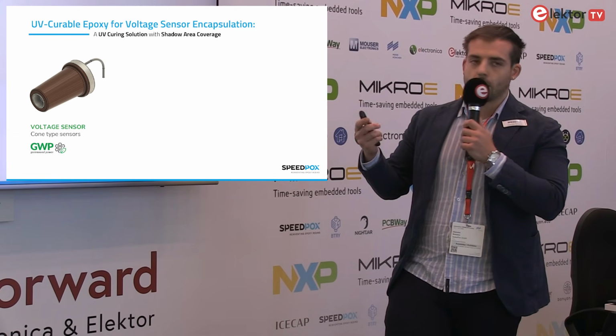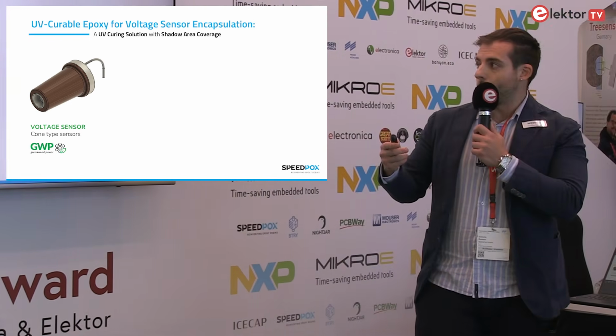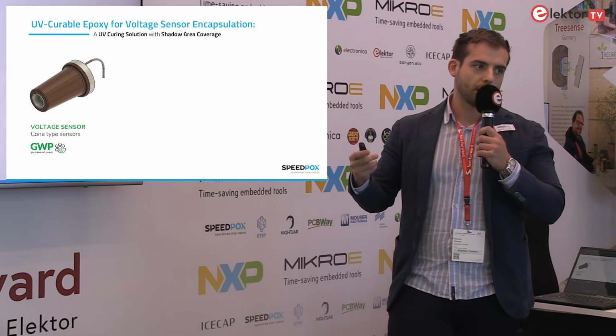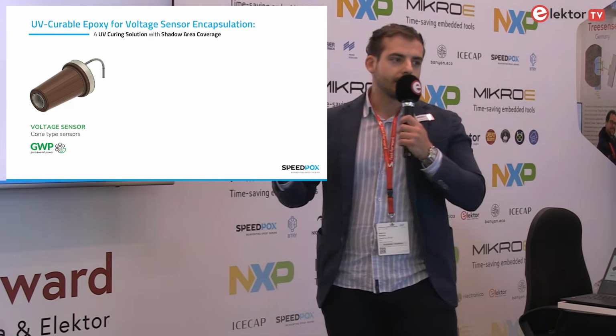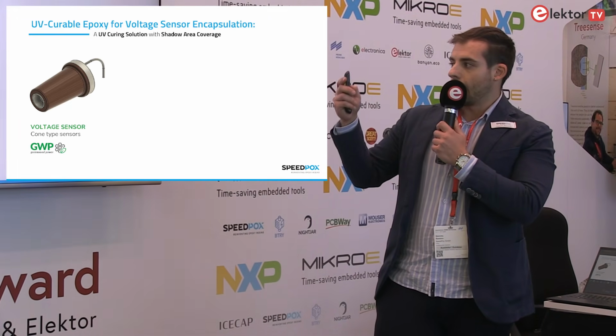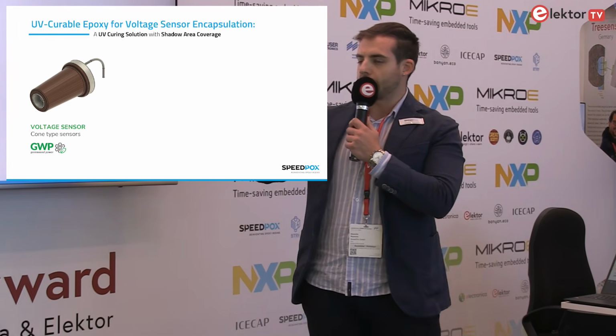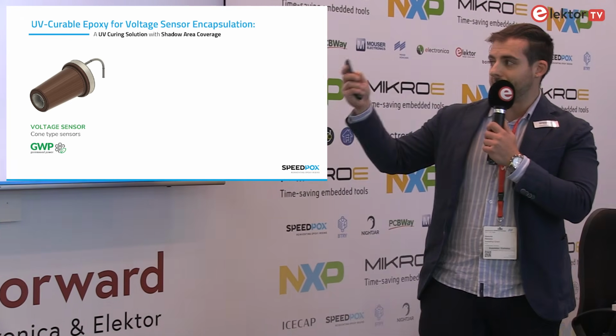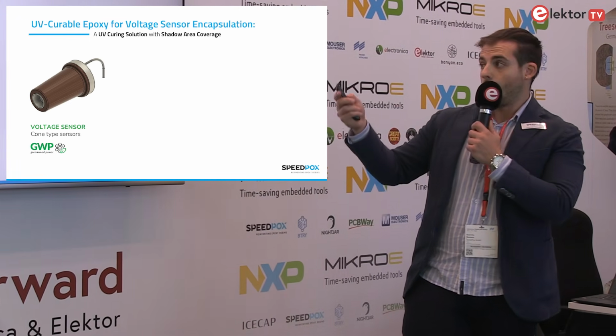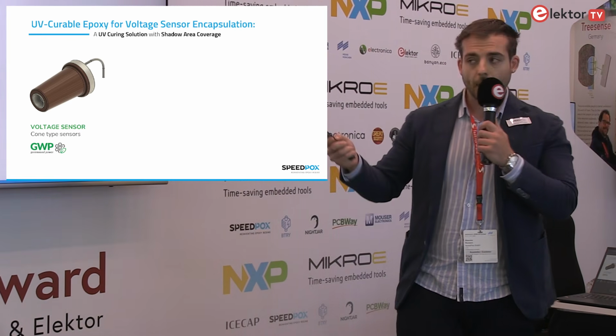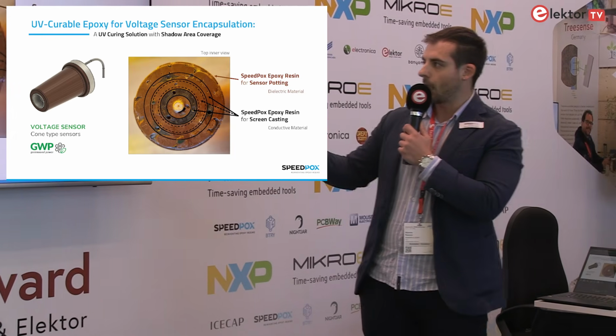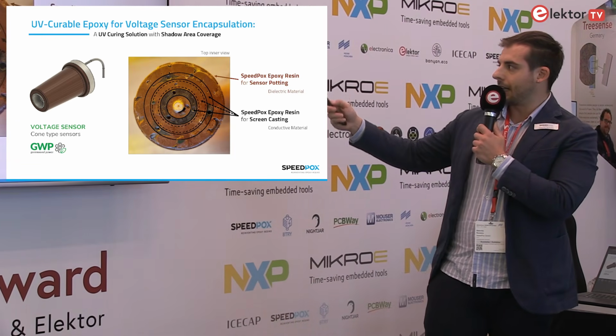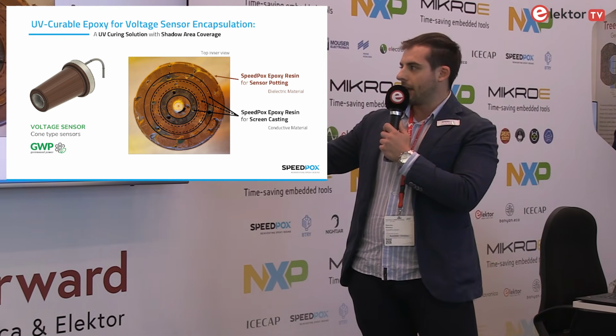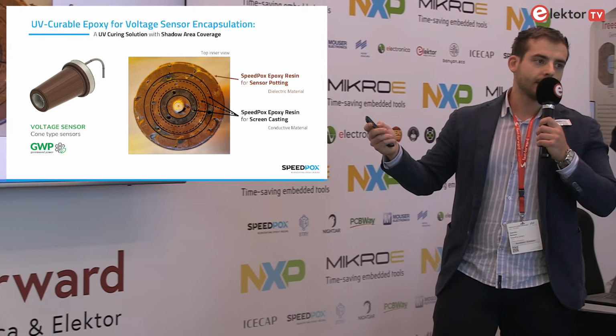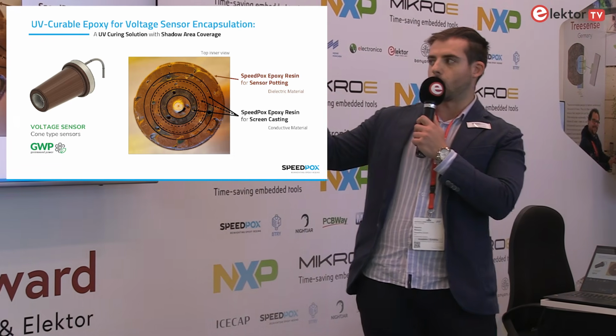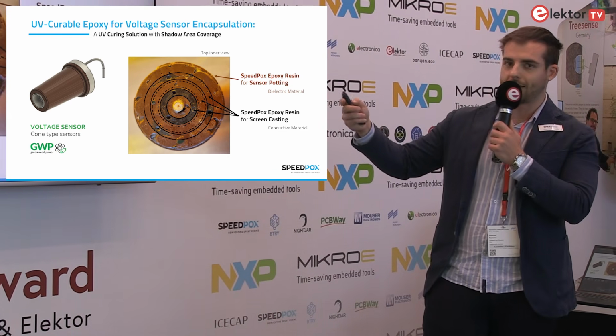So GWP had one issue. They wanted to scale up the production, but they couldn't increase the dimensions of the company because of restrictions and limitations. Because of that, they smartly thought to work on the main factor that restricts the production, that is the epoxy resin, the curing time of the epoxy resin. They got in contact with us, and for them, we developed two new products. We refined the resin, the brown one, the dielectric material, and also a conductive resin that is inside, the black material. With this, they managed to increase the production of this single sensor by 6 times.